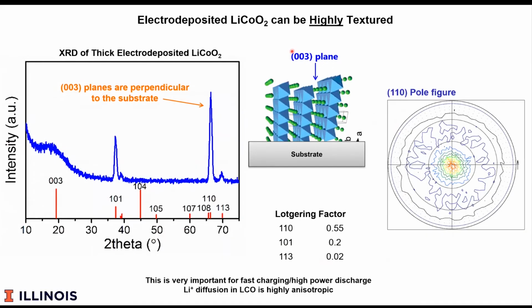Okay, so I mentioned a little bit about texturing, and now to give you a little bit of an idea of just why it's so important. Here we're looking at the crystal structure of O3 lithium cobalt oxide, and as you can see, these are the (003) planes, and the green are the lithium ions. The lithium ions move very rapidly in this direction, but they move quite slowly in the lateral dimension because they don't make it through the blue layers very effectively. It also turns out that the electrical conductivity is faster by a few orders of magnitude in this direction.